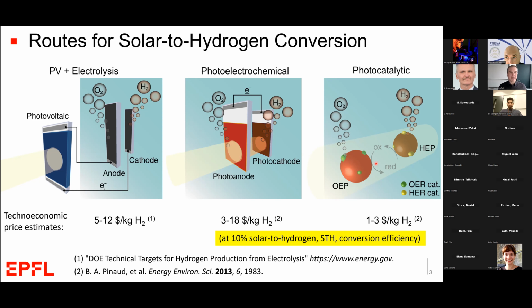Alternatively, this particle-based photocatalytic approach, where we simply take semiconductor nanoparticles or microparticles and disperse them into water, really has an opportunity to produce hydrogen at a drastically less expensive cost. Again, assuming we can achieve reasonable solar to hydrogen conversion efficiency. So unfortunately, the current state of the art with these types of particle-based systems is quite low.